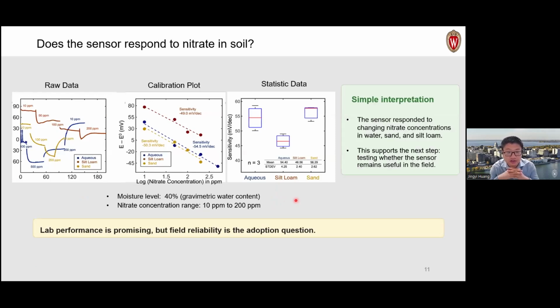Once we developed this sensor, we also tested its performance with different soil textures, because we noticed that different soil particle sizes may have different effects on the sensor performance. In the calibration experiment, we noticed that for different soil textures, the sensitivity of the sensor to the nitrate ion change in the environment could be slightly different. The sensor works more strongly, more functionally, in the sandy soil compared to a heavier texture soil like silt loam. The sensitivity is reduced a little bit because the heavy texture soil has more clay particles, which will create a different calibration relationship with our sensor material. So we know that our sensor can work in different soil texture environments in the lab.